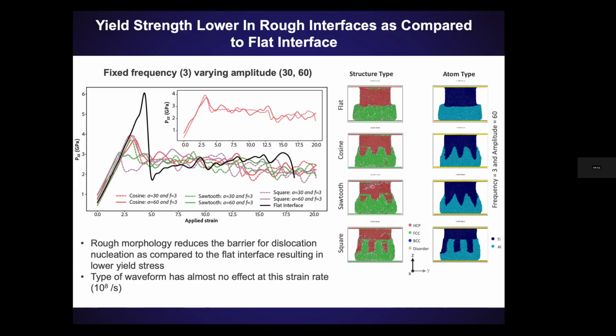So I wasn't going to pay much attention to it, but what I really just wanted to point out is that you're getting a lot of dislocation nucleation from these rough interfaces as compared to the flat interface, where the aluminum is just kind of mushrooming around the titanium. And remember, these are all perfect systems that we started with, so there are no pre-existing dislocations. And that's why the yield stresses are really high too.